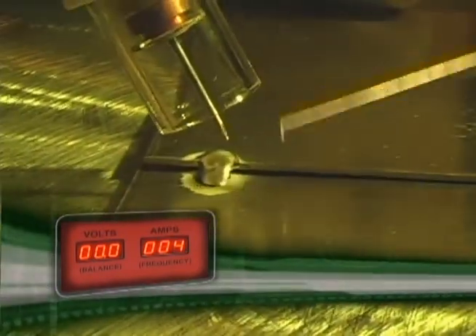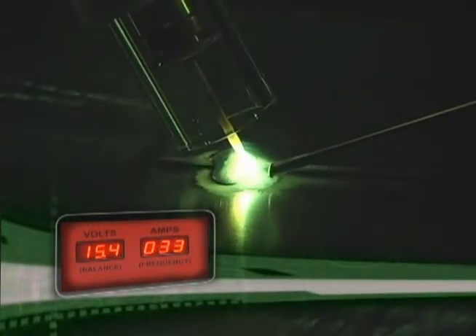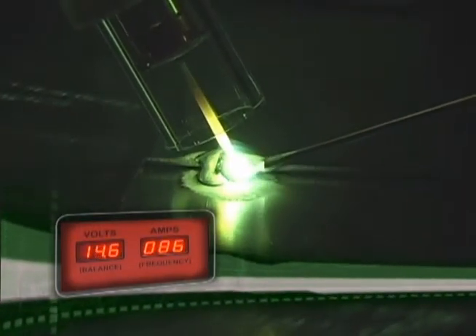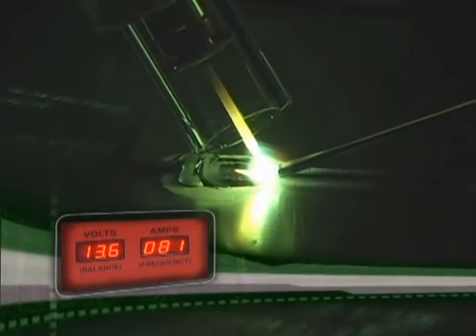Once the panels are tacked, the easiest place to start your bead is on a tack weld. Get a molten puddle and start moving. Again, dab the filler metal into the molten puddle.